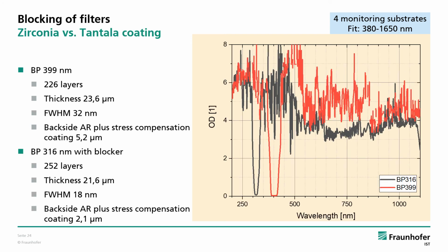The broad blocking range of the filters in terms of optical density is plotted in the graph on this slide. It is defined from 200 nanometers to 1100 nanometers. We see one of the tantalum filters in black and one of the zirconia filters in red. The overall optical density should be better than OD3 and reaching OD5 next to the bandpass area and at several wavelength ranges of higher order lines.